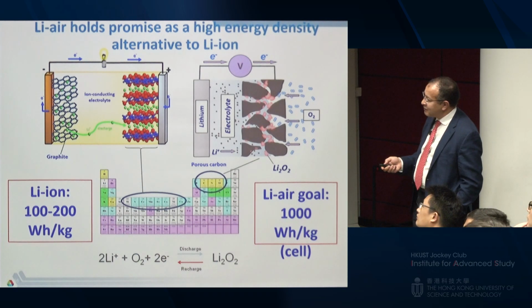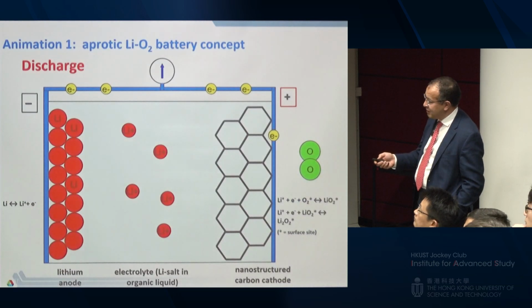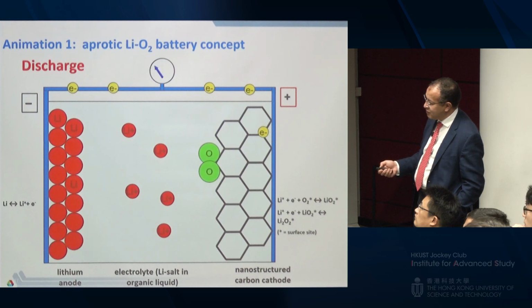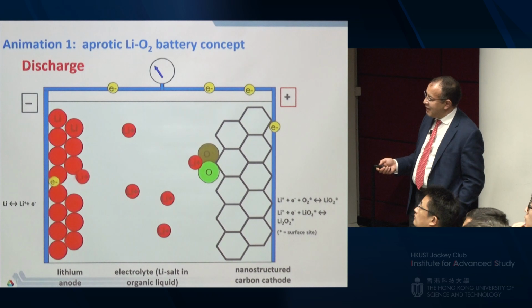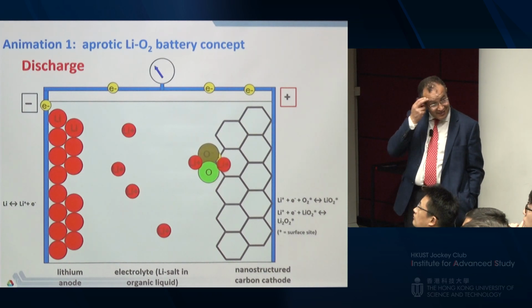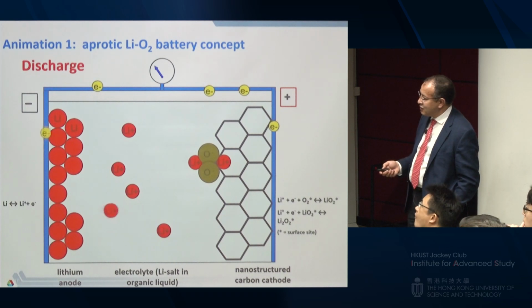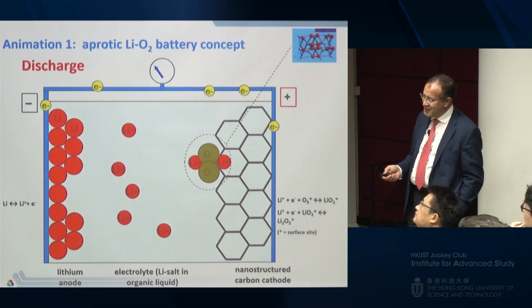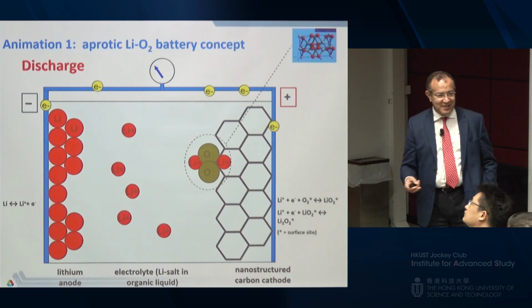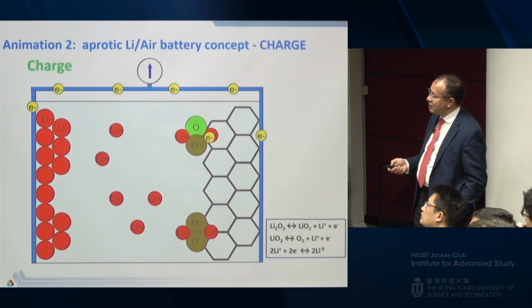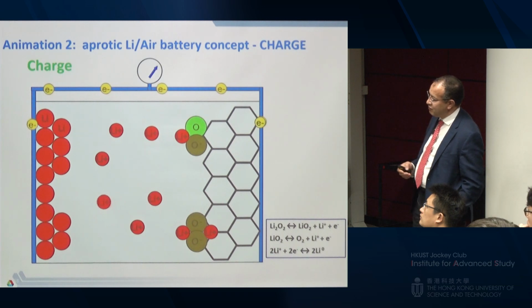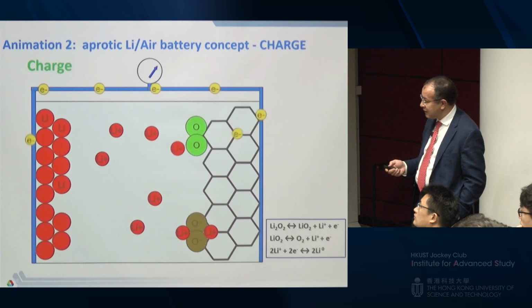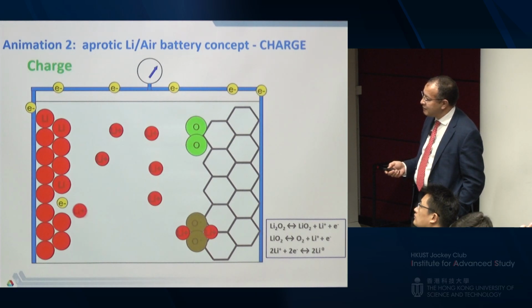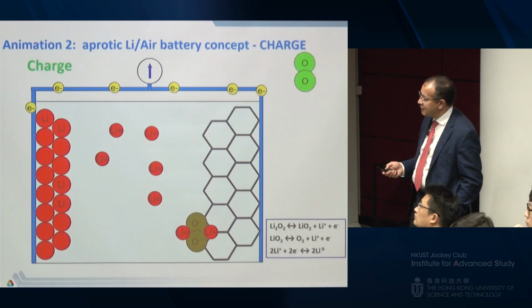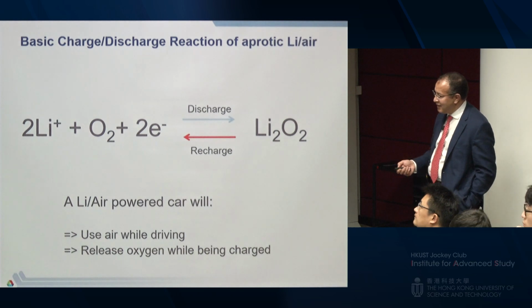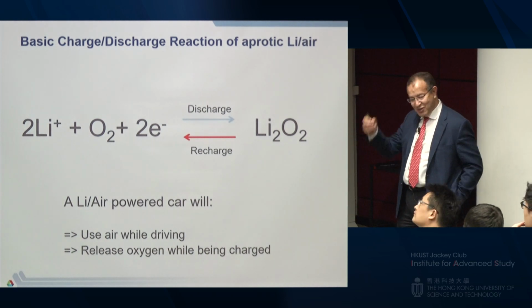This is how it works. For people who don't know, basically when you start discharging, you have the first electron transfer to form a superoxide, and then the second electron transfer to form a peroxide. And then during charge, you basically dissociate those bonds, which is extremely difficult because the peroxide is resistive, insulating. So when you do the charge, you move the first electron to dissociate the first bond and then the second bond, and you end up with oxygen out. So in another word, use air while driving, if you use it in an electric vehicle, and release oxygen while being charged. Can be better.